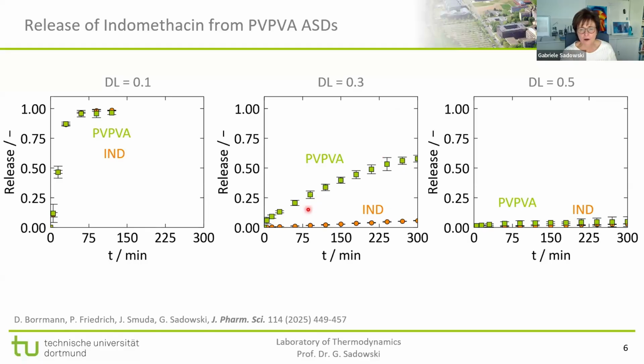What we also see is that now we have not the polymer and the API getting released at the same time as before. This is what pharmacists call a congruent release. And this is what they call a non-congruent release. So that means the two components which are homogeneously distributed in the tablet are not releasing at the same time and the same rate, but here the hydrophilic compound PVPVA is still released and much better released than the compound we would really like to get into solution. So the indomethacin release is quite bad and it's very, very small compared to what we originally had.